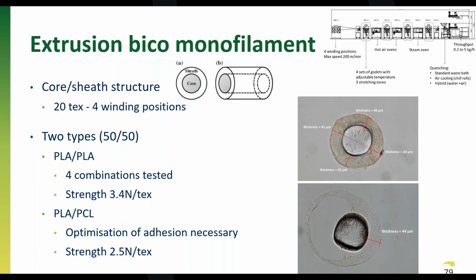For the PLA PCL, you can also see a picture, but here we had some problems with the adhesion. As Alejandra also already mentioned, the adhesion is very important between the different materials. And we did some optimization on that to exclude the voids that we get here, and we succeeded in producing a nice round core-sheath structure filament. So that is okay now, with a strength of 2.5 Newton per tex.